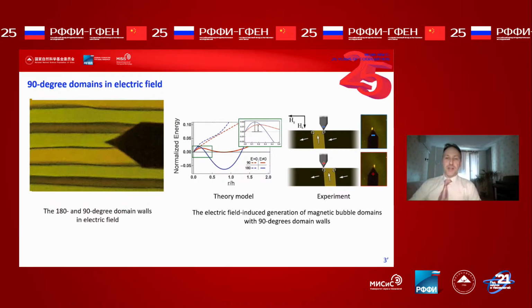When the voltage is applied to the tip electrode, the domain walls are displaced from the equilibrium position. And on the right side, we can see an even more pronounced effect, the nucleation, the generation of new domains by electric field. When you apply negative voltage, it appears on the left of the tip. When you apply positive voltage, it appears on the right of the tip.